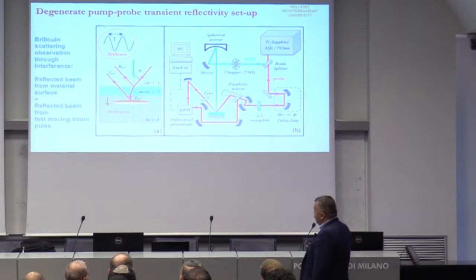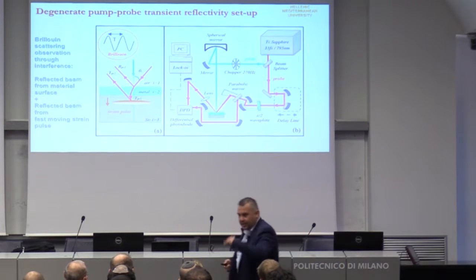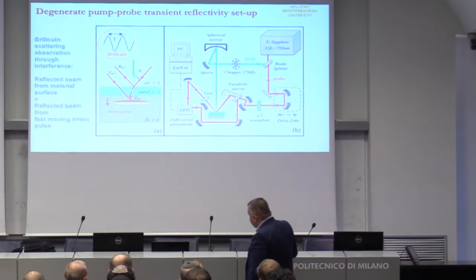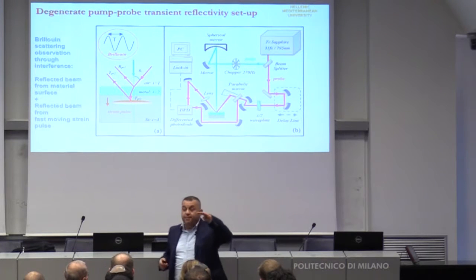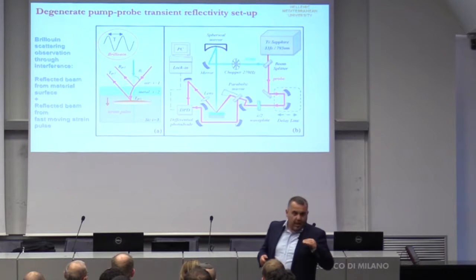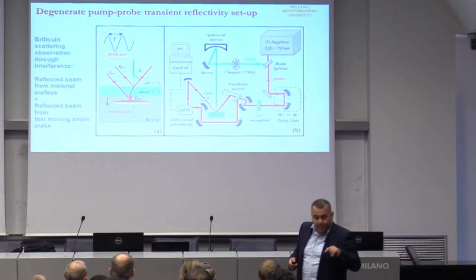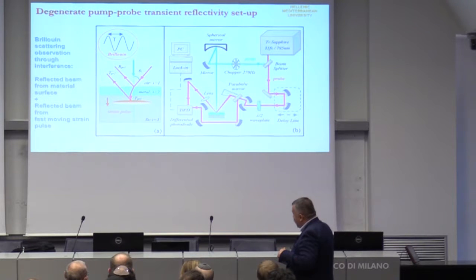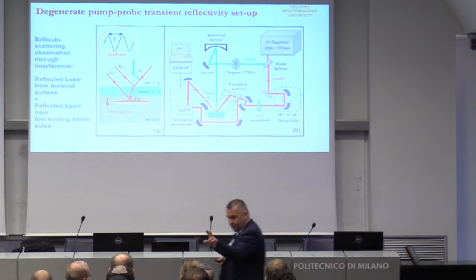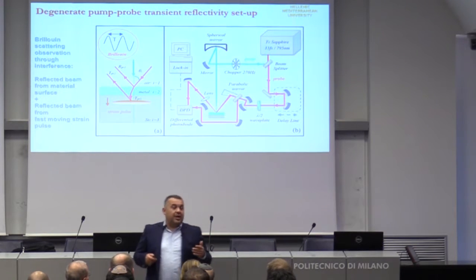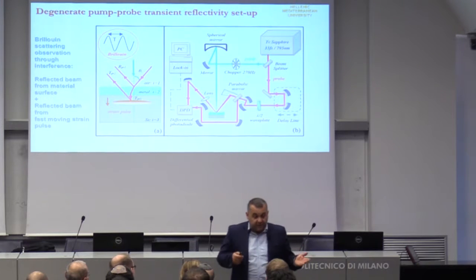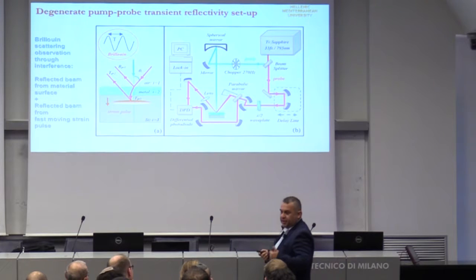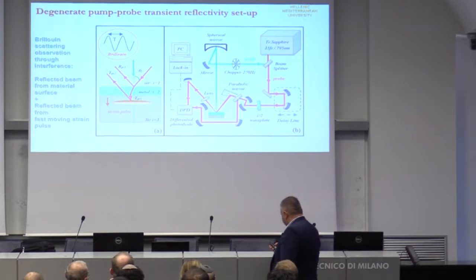Here the pump beam generates the strain. The strain propagates inside the multi-layer material. Here is the probe beam. There is a reflection of the probe beam from the interface surface, and there is also a reflection of the probe beam from the moving strain. Depending on the delay between pump and probe, there is an interference between these two reflections, which is positive or negative, constructive or destructive interference, and this is actually the Brillouin scattering. See here, for example, some results.